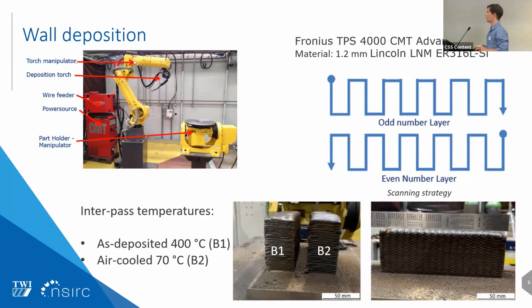The first wall, which we call wall B1, is in the as-deposited condition, meaning we didn't implement any cooling between each layer of the deposit. So we reached an interpass temperature of 400 degrees Celsius. The interpass temperature is defined as the temperature of the top surface just before the next layer is deposited.